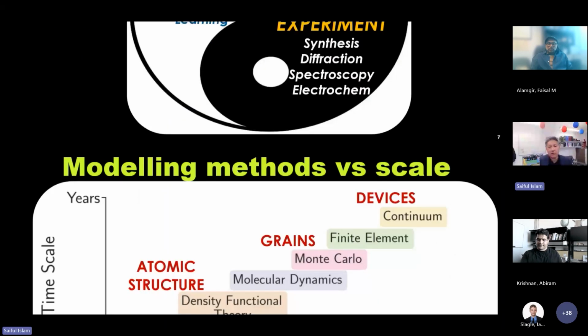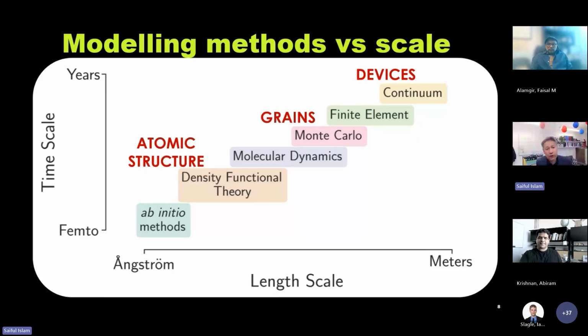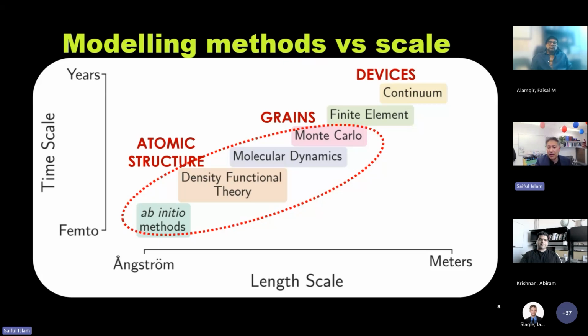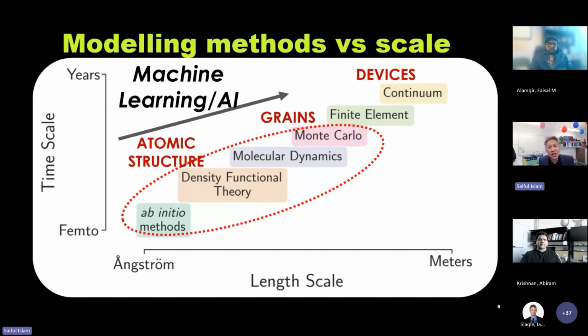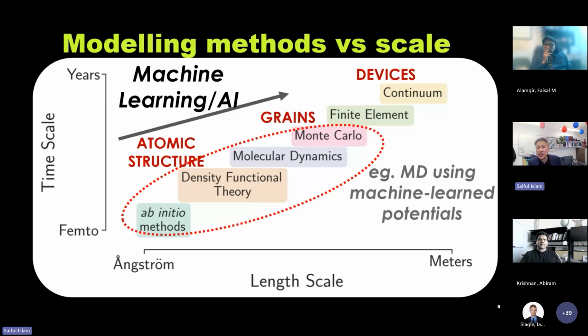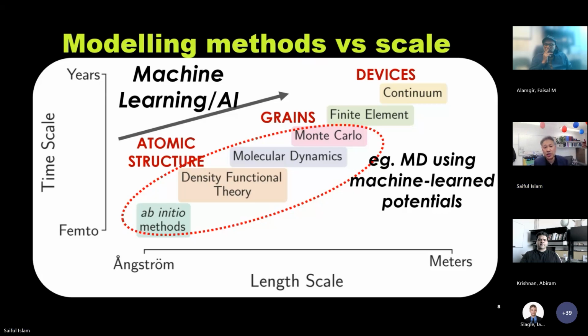So what about modeling techniques themselves? I'm showing you here a plot of time scale along the y-axis and length scale along the x-axis. And you can see different techniques, ab initio, density functional theory, molecular dynamics, Monte Carlo, finite element, and continuum. And basically on the bottom left is the atomic structure. In the middle, we've got particles and grains. And right at the top right are devices. And I fall in the bottom left, very much the chemistry and materials side of things, where we try and understand the atomic and particle structure. But increasingly, we're using machine learning and AI tools to try and bridge the gap between ab initio and larger length scales. For example, we're using molecular dynamics techniques using machine learned interatomic potentials.